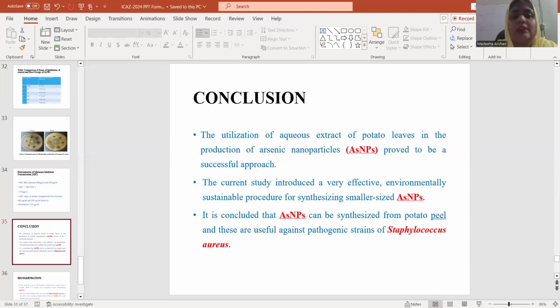Conclusion: the utilization of aqueous extract of potato peels in the production of arsenic nanoparticles proved to be a successful approach. The current study introduced a very effective, environmentally sustainable procedure for synthesizing smaller sized arsenic nanoparticles. And from this research, it can be concluded that arsenic nanoparticles can be synthesized from potato peel, and these are useful against pathogenic strains of Staphylococcus aureus.